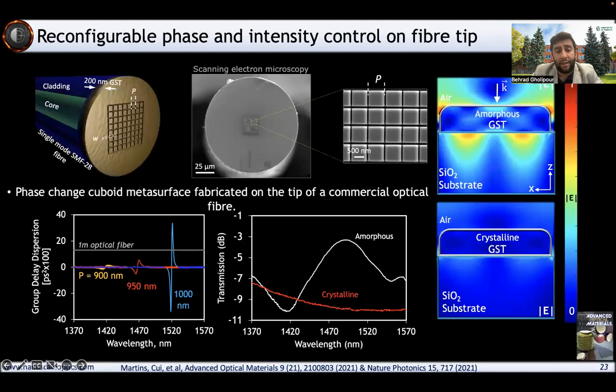So just a couple of slides, just opening up the fiber side of things. As I said, we can put these on the tip of optical fibers and create very nice tunable devices. This is a particularly interesting device. In this case, we have a switchable metasurface on the tip of an optical fiber. This is a scanning electron microscope image of the fabricated device, and you can see that by changing the period of these little cubes, we can change the wavelength of operation and create very high group delay dispersions, the equivalent of a 1 meter optical fiber in a 200 nanometer tip of a fiber that we can switch and collapse back and forth. So these are great for phase shifters and intensity modulators in a very compact environment. You can ditch the chip and put everything on the fiber itself.